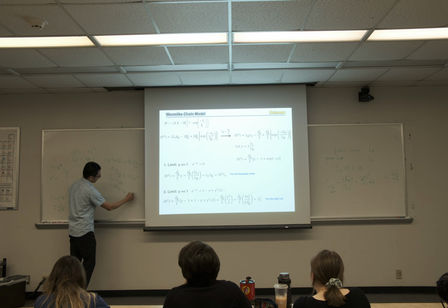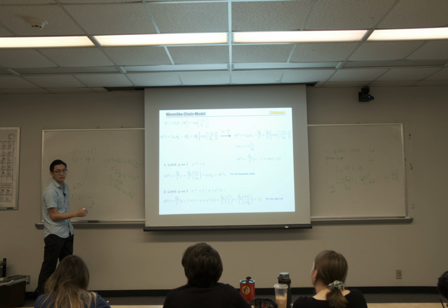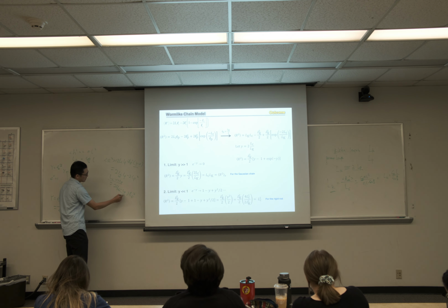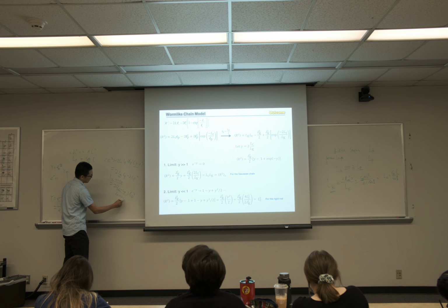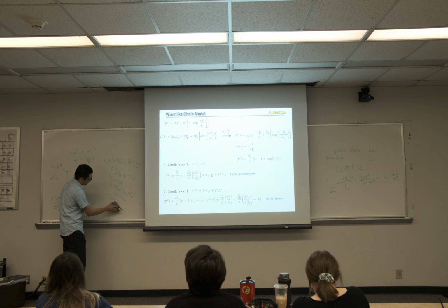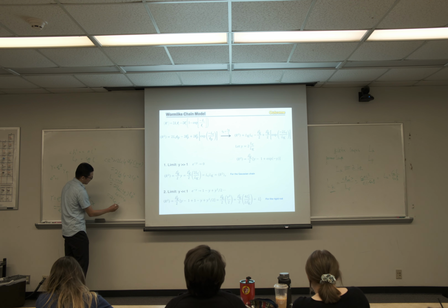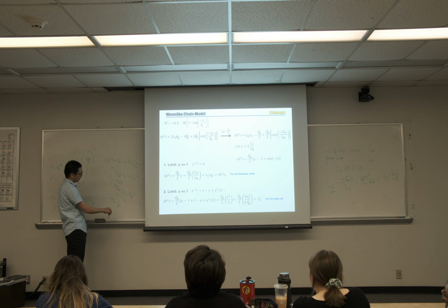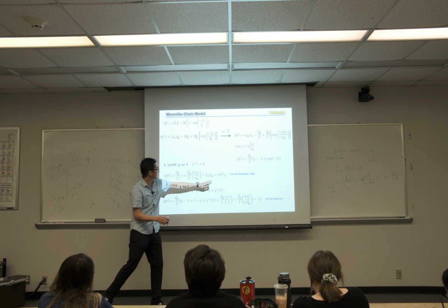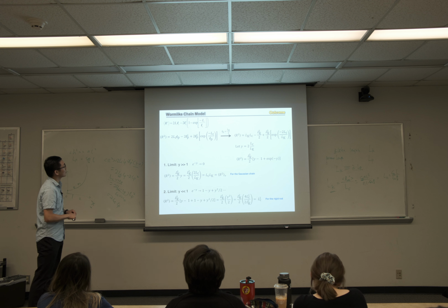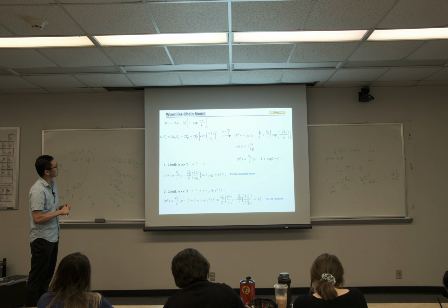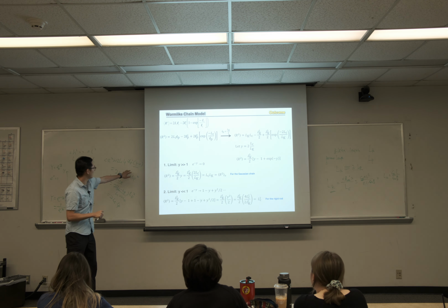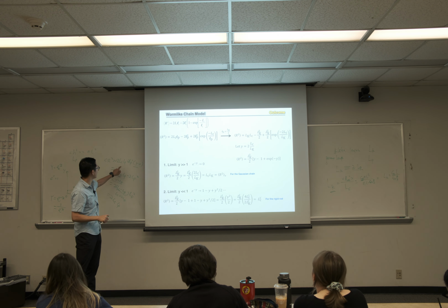We can write it this way. Is it clear? If LC is much bigger than LP, we can basically write it as twice the contour length times LP. And it basically goes back to what we started with. So basically you're just saying the second term is effectively 0? The second term is effectively 0. It's much smaller than LC times LP.